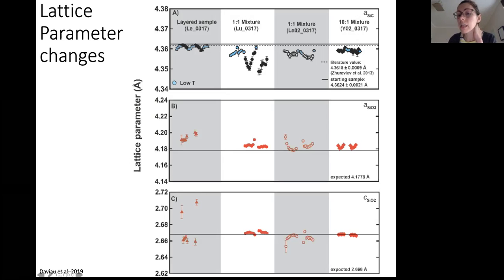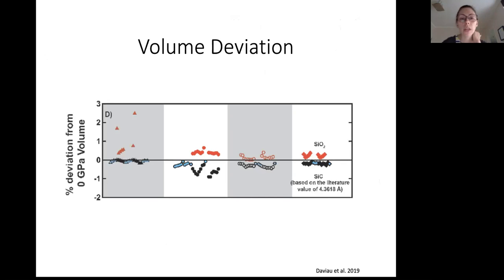Correspondingly, the silica is a little bit larger than you would expect it to be in a lot of these patterns, with most of the changes happening in the A parameter, the lattice parameter. All right, so if you then look at the volume deviation and compare how silicon carbide and silica are deviating from their expected volumes, you see that silicon carbide is generally on the smaller side. It's a little bit smaller than you would expect. And silica is a little bit larger.